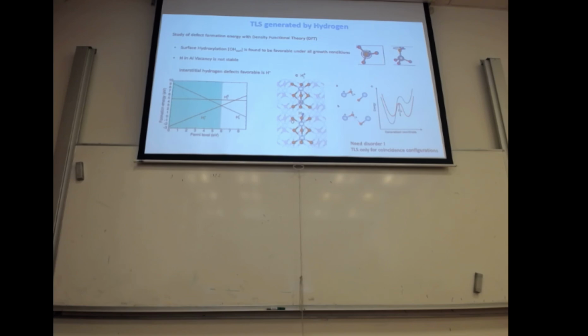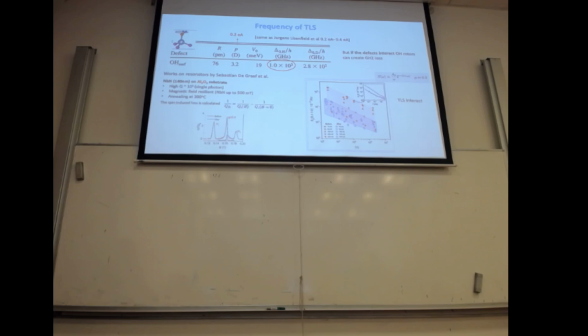So in order to have a two-level system that we care about from this interstitial hydrogen, somehow your hydrogen needs to get very close to two oxygens, so that this double-well configuration becomes something degenerate, and so you can have this easily activated two-level system. So you see, you really need to look for a particularly coincidental configuration. And now comes another big problem.